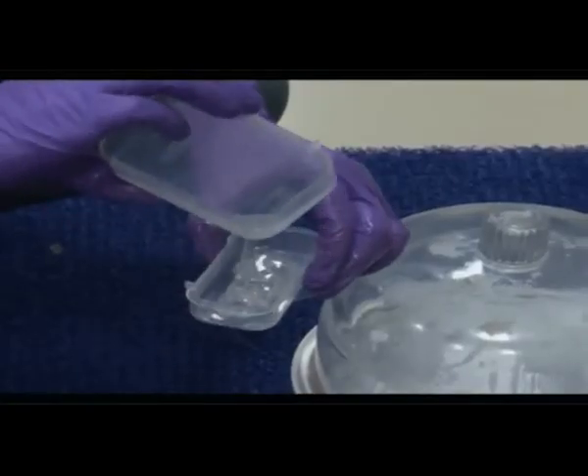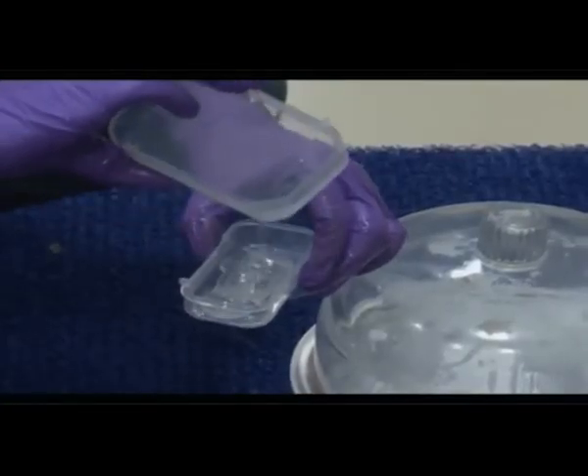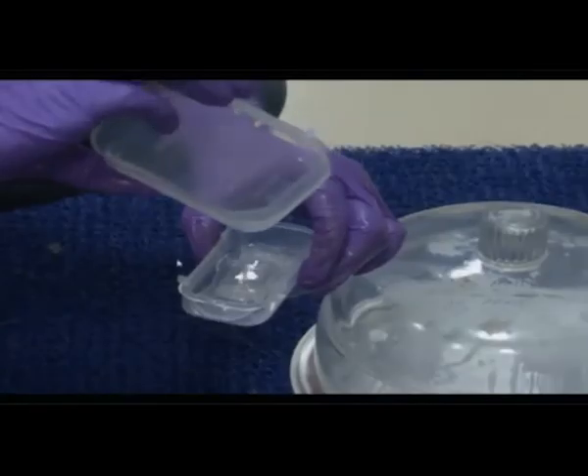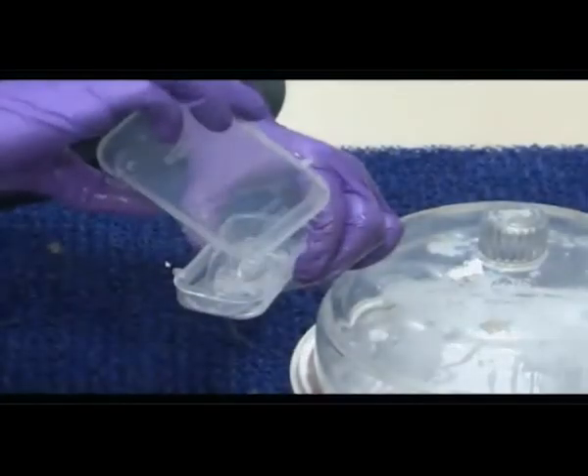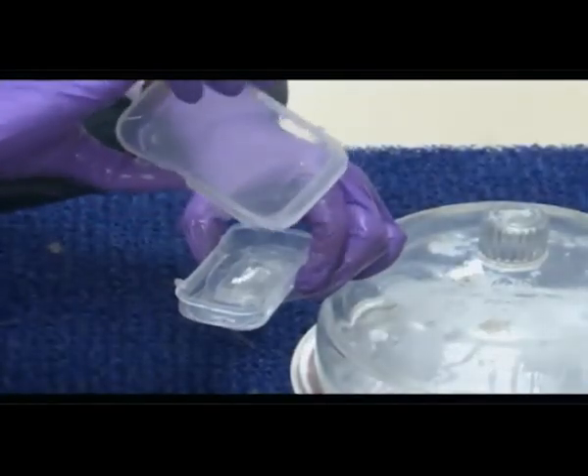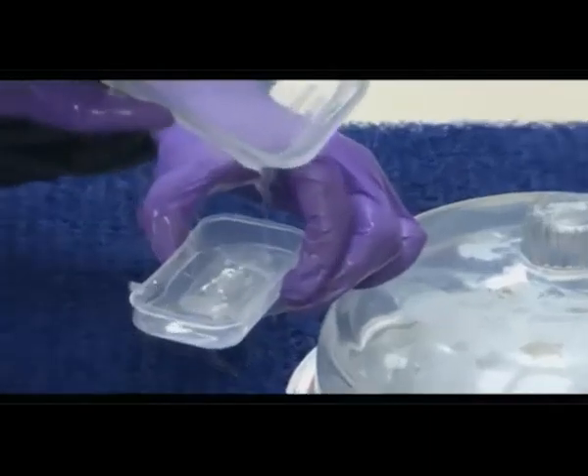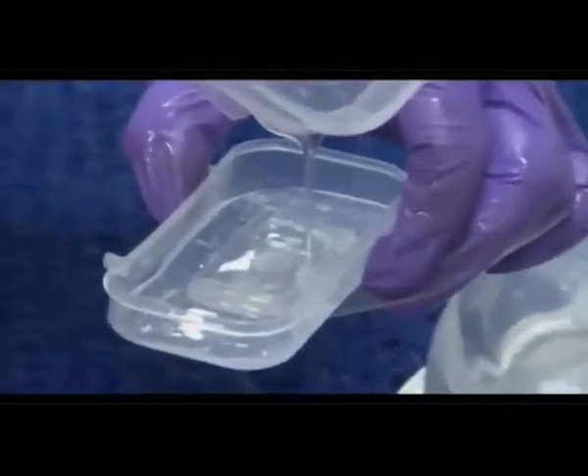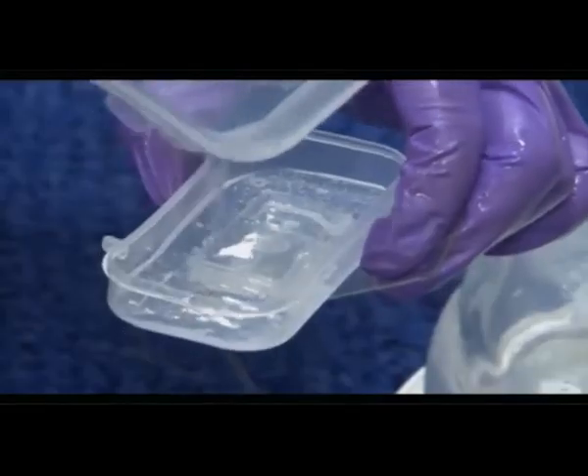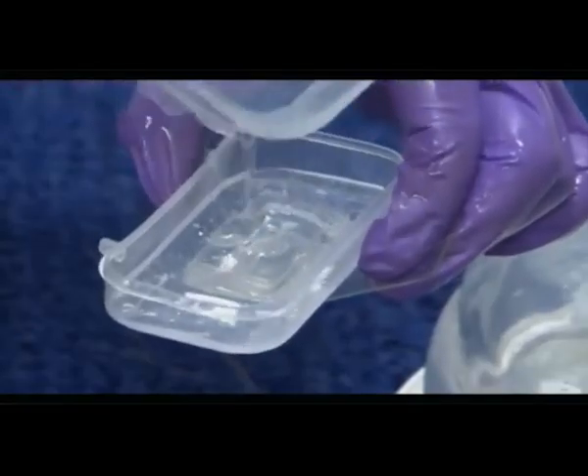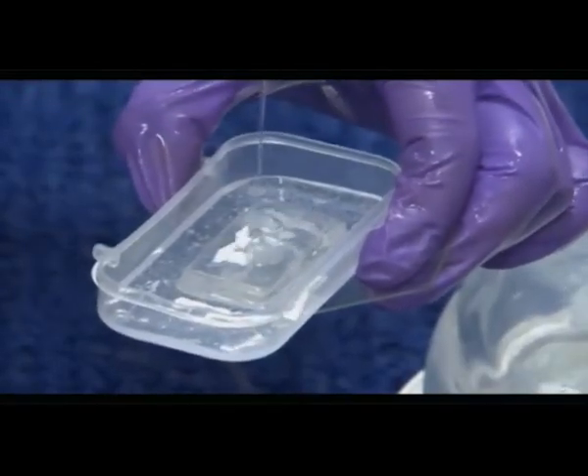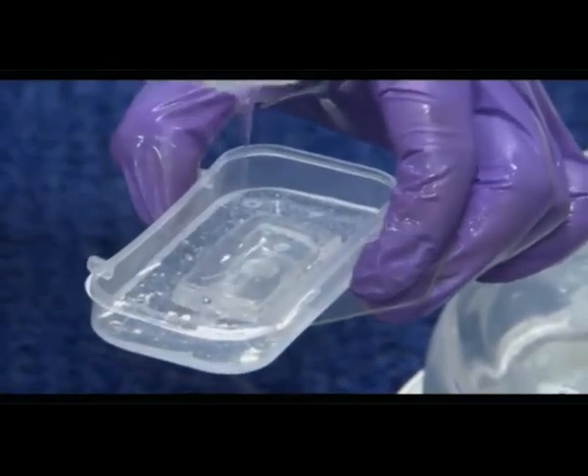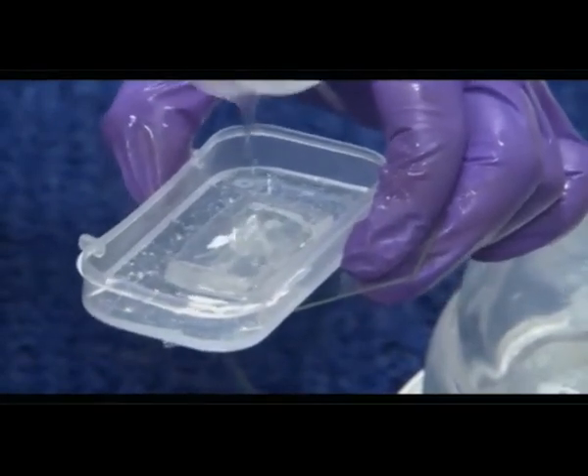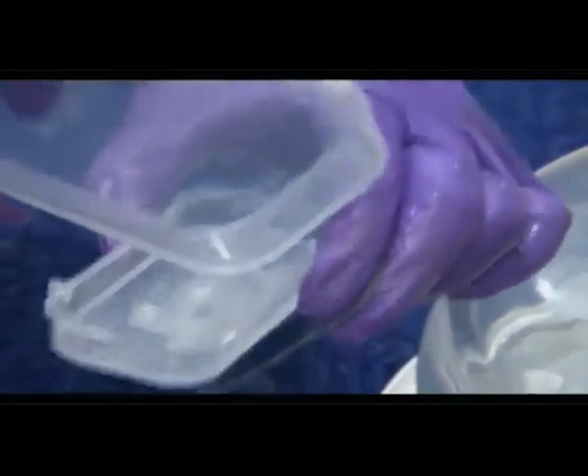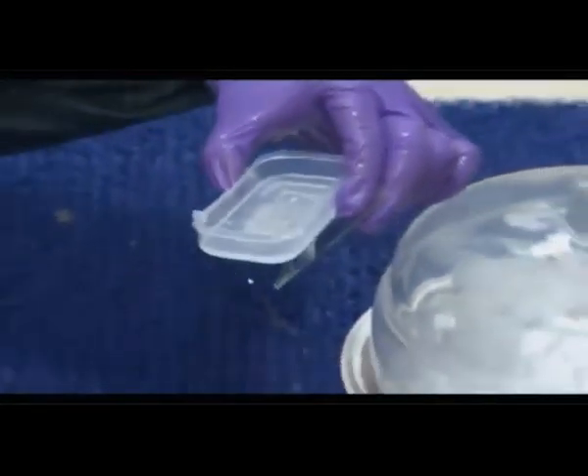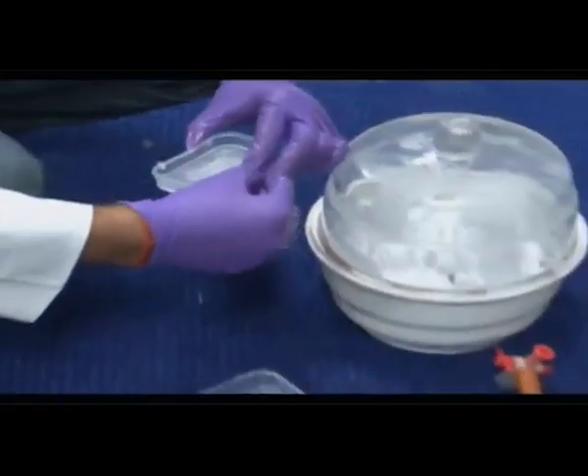Pour it in a manner so that it covers the entire pattern, okay, and there is a little bit of PDMS remaining on the top, which defines the film thickness that you would eventually need to use on the top of this material. So you can see already a lot of bubbles being entrapped on the surface of this PDMS, and the idea is that you have to have some desiccation and some other steps so that these bubbles can be somehow gotten rid of, so that you can have a clear matrix, a visibly clear matrix of PDMS in this particular zone.